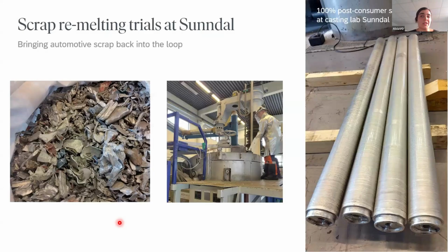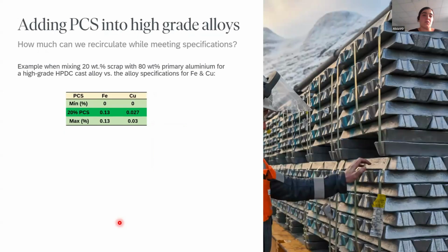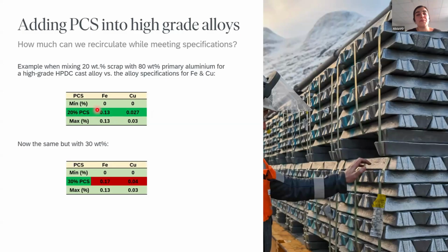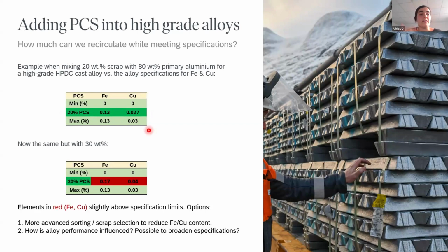And then, for example, in the laboratory in Sunndalsøra, we do some smaller scale tests like this one, where we were testing scrap coming from the automotive industry, from shredded cars, and trying to use it for primary foundry alloy used for the automotive industry as well. This is an example of typical specifications that we have in primary foundry alloys. They're quite strict in iron and copper, and these are present in the post-consumer scrap. So we calculated we could add up to 20% of this type of scrap, but if going higher to 30%, we would be going outside of the specifications. So we are trying to understand how to either improve the sorting process or how this increased concentration of elements would affect the properties of the final products.